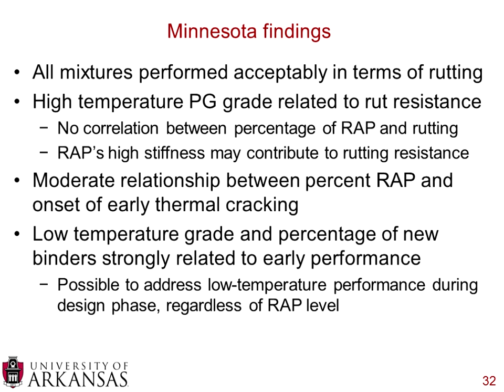They found only a moderate relationship between percent RAP and the onset of early thermal cracking. So we talked a little bit about different fracture tests, which are able to quantify cracking. And most of those laboratory tests found that as you increase the RAP content, you're increasing the susceptibility to cracking. But Minnesota found that they didn't have a very strong relationship between the percent RAP and the onset of thermal cracking.